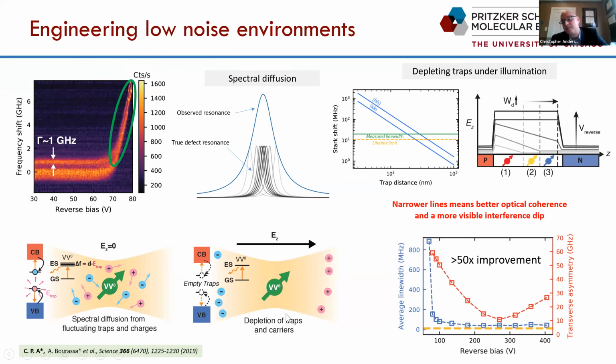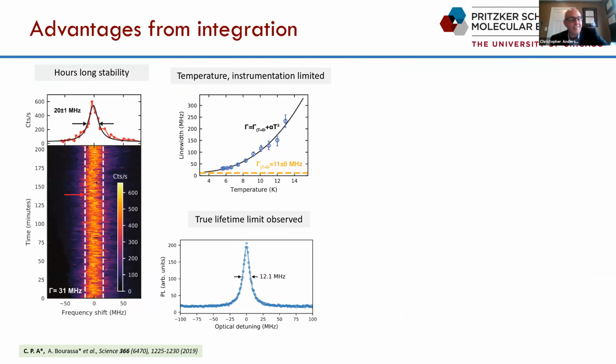So one of the things that we tested essentially is that this transverse asymmetry, basically what the excited state orbitals look like, had a very different structure where essentially the asymmetry kept going up, but the line width kept going down. So at least as far as we could tell, there wasn't an easy way for us to connect the electric field's effect on where the orbitals were and the line width narrowing. But I'd be curious to hear your thoughts on that later. Okay, interesting. Thanks.